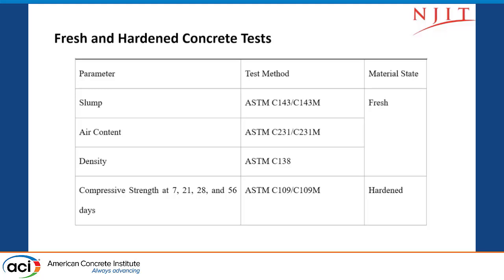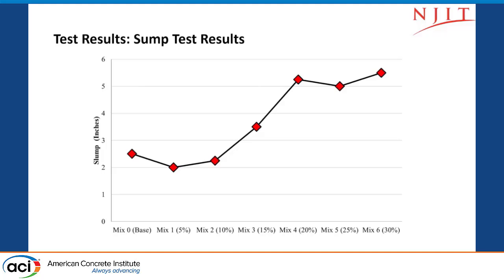Of course, we followed the fresh and hardened concrete tests from ASTM: slump, air content, and density. And we did the compressive strength at 7, 21, 28, and 56 days. So this is the test results for the slump.